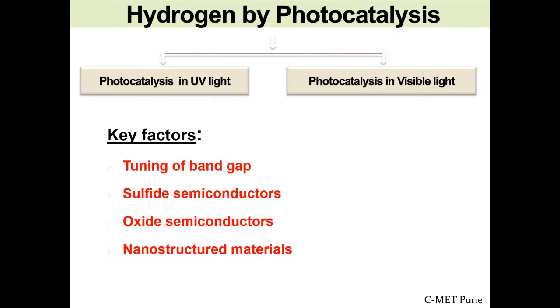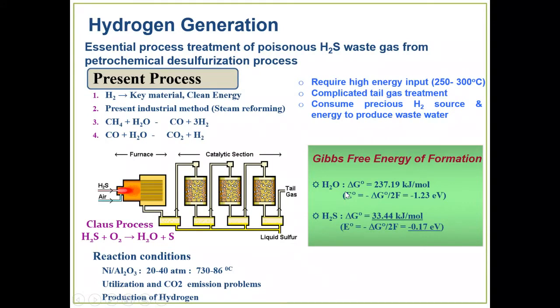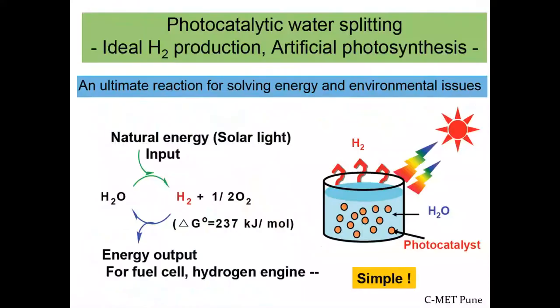See the thermodynamics of water splitting. Delta G0 is 237.19 kilojoules per mole. A huge amount of energy is required to split water into hydrogen, but still it is possible through this process. For H2S it is only 33.44, a very small amount of energy is required for the splitting. So this is the process. At room temperature, we can have a catalyst in the water. We can expose it to sunlight. The sunlight falls on the particles, and photoexcitation takes place. In these semiconductors electrons and holes are generated. During this process, holes are trapped. Some sacrificial agent can be used, and the hydrogen generation efficiency can be increased.